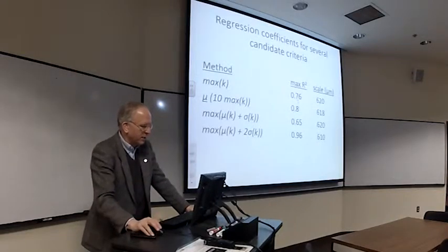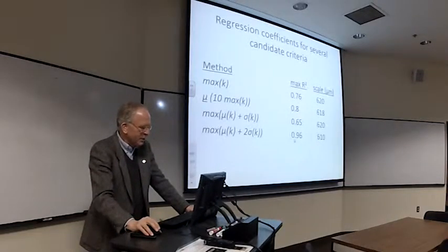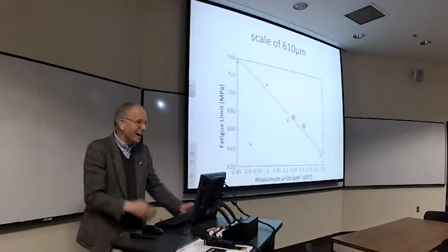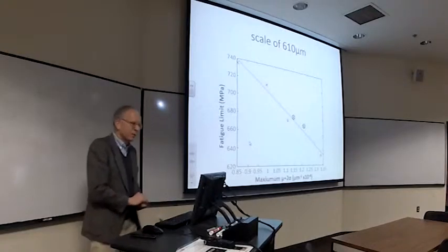And then right near the end, I said, how is it going? She goes, oh, well, I got another one that's looking pretty good. And I said, you should have called me in the middle of the night, 0.96. That's amazing. So this is a very exciting result. So you take the maximum of all the means of those and add two standard deviations. And that was the combination that did this. And intuitively, this makes a little bit of sense because it's the worst one that's going to get you. And so we had tried just the worst one too, and that didn't work very well.